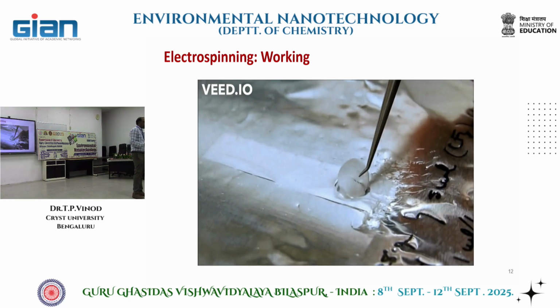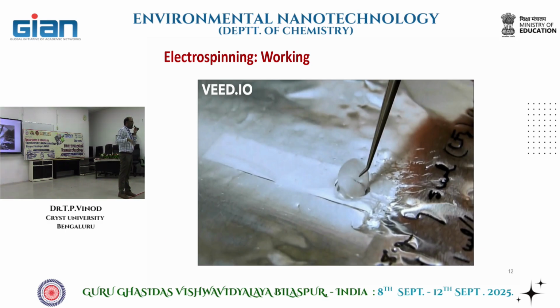Yeah, it's very different. In spin coating, you are just rotating it, and due to the centrifugal force, you have this uniform deposition. Here, the internal structure is very different. You have nanofibers. In spin coating, it's just a uniform film without any pores.